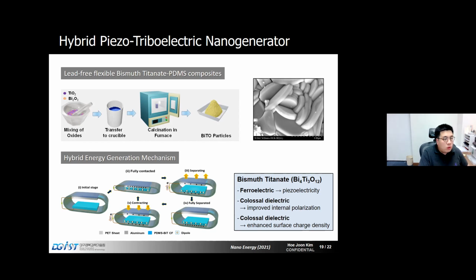So before, when people were trying to combine these two different techniques, they built an individual piezo device and a different tribo device, and they just connected them in series and said, oh, this is a hybrid system. But I believe that is a good approach, but it's not the best approach. So our approach was, why don't we select a good material with good properties for both piezo and tribo effect, and build a single device which can enjoy both piezo and tribo effect. So we tried this internal hybridization concept.